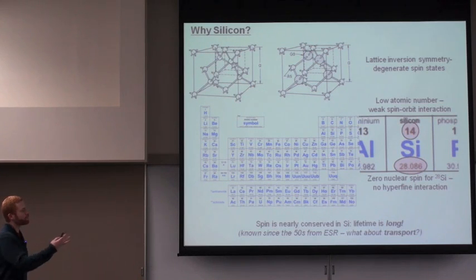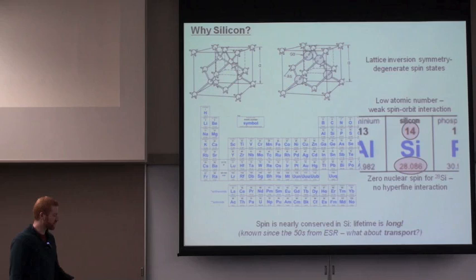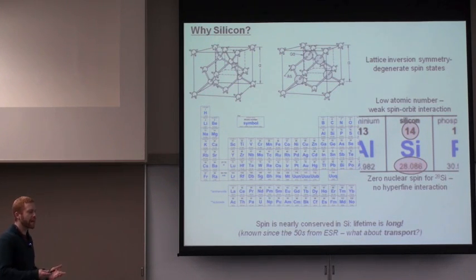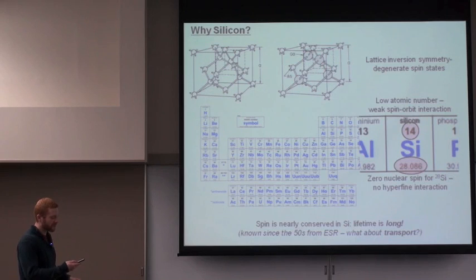Now, the direct, one might even say the naive approach, the way that one might come up with to do this when first approaching this problem, would be simply to take a spin polarized source, a material which has an imbalance of spin up and spin down electrons even in equilibrium, and just take this electron population, which is already spin polarized in equilibrium, and push them across an interface into this non-magnetic material, silicon. And I'm going to tell you about the consequences of analyzing this process, and then show you that this is actually not going to work, and again, show you how we circumvent this.